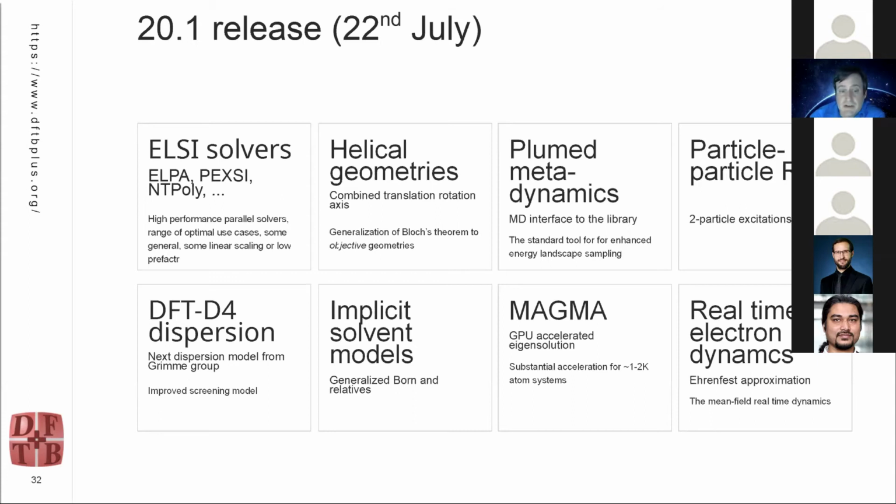We can also do things like real-time electron dynamics. So this is one way to get access to excited state properties, because if you have the dynamics in time, the Fourier transform of that tells you about the energy of the excitations in the system. But you can also use this as literally a real-time evolution of the electronic states of the system, and have a look at what's going on. For example, when you perturb a system and you watch charge flow around inside of it. Now, Ehrenfest dynamics technically are a mean field approximation of what's really happening, but it's quite a powerful way to